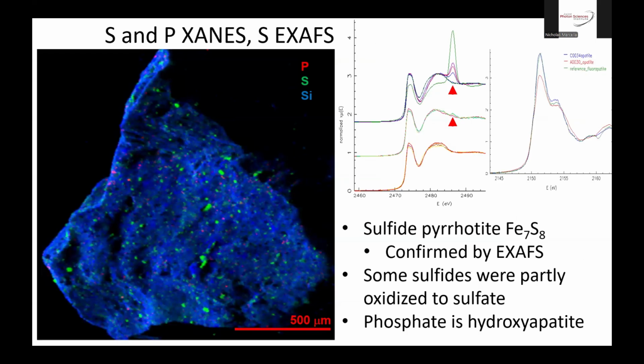And the sulfides, we did XANES of the sulfides, and they fairly closely matched with the mineral pyrrhotite. But we confirmed that with full XAFS because there are a lot of different sulfides that are fairly close. So we wanted to distinguish that. And you see that some of the spots that we measured showed a peak marked by the arrows at a higher energy, and that indicated a partial oxidation of the sulfide to sulfate. And that probably happened by exposure to air. So it's not native to the sample. So with some samples you have to be careful of sample handling and sample preparation before interpreting what you see.